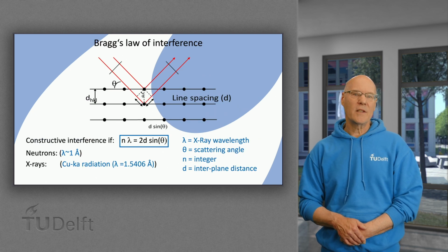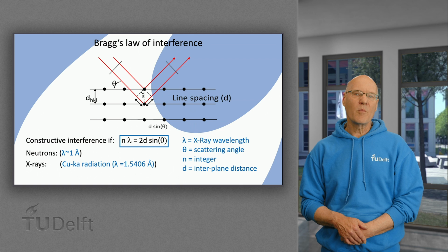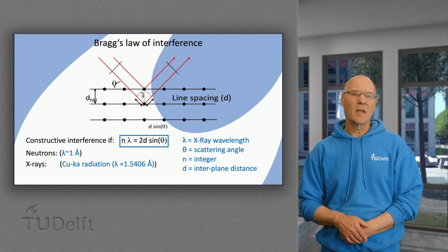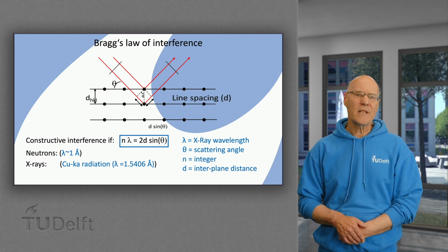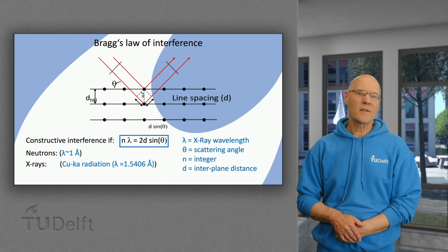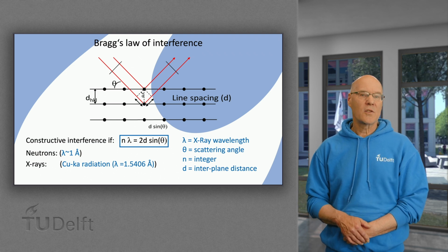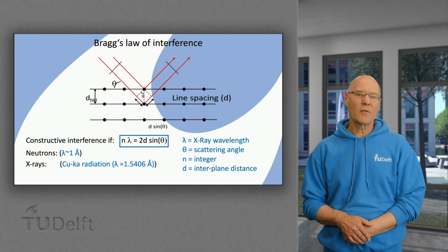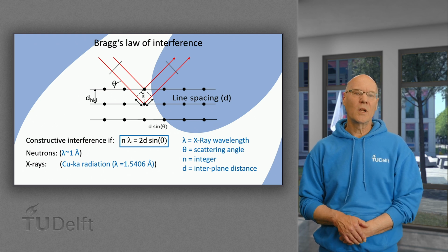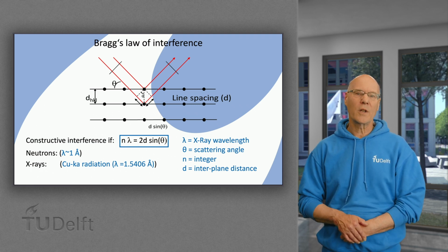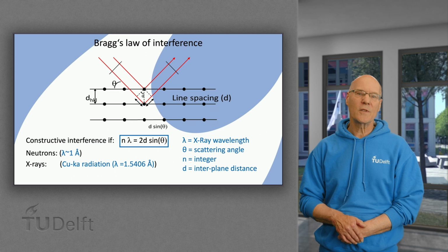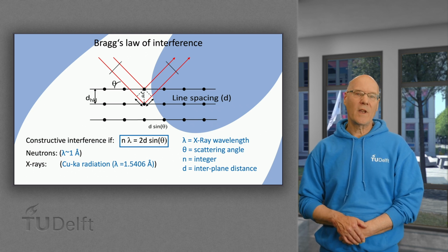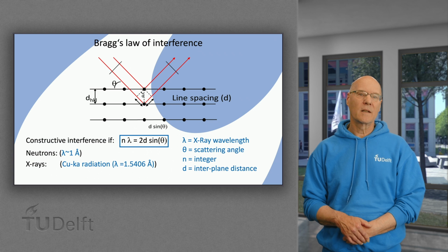Apart from the difference in scattering properties, neutrons have a much lower energy compared to X-rays, millielectron volts versus kiloelectron volts. Hence, there is hardly any risk of thermal damage of sensitive samples. Similar to X-ray diffraction, observation of neutron diffraction signals also requires long-range order, and so constructive interference occurs according to Bragg's law. Thus we will typically record it as a function of 2 theta, where the peak position gives information on the lattice spacing.